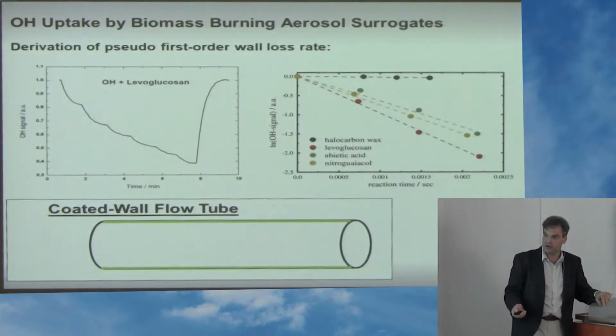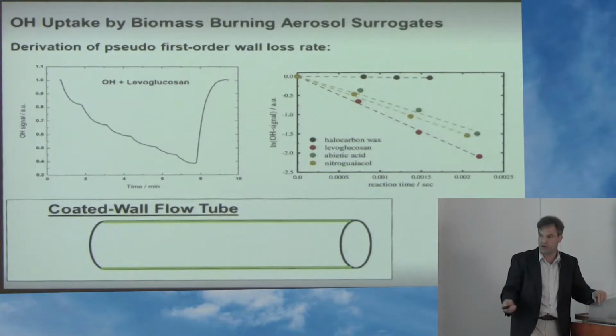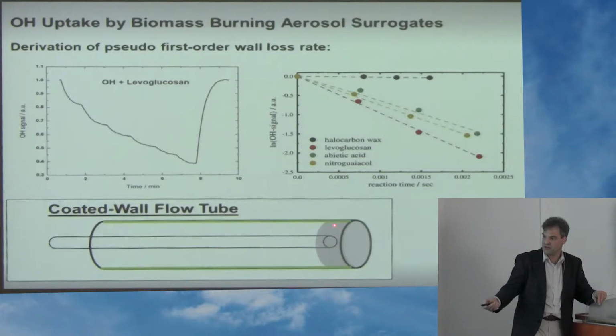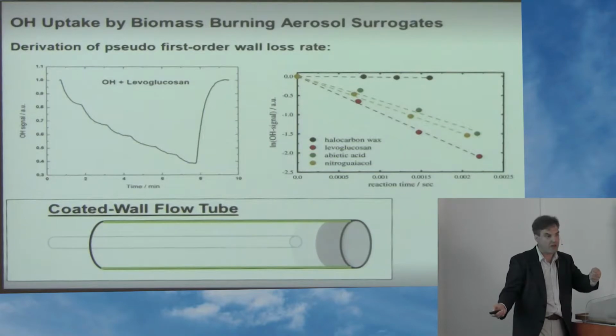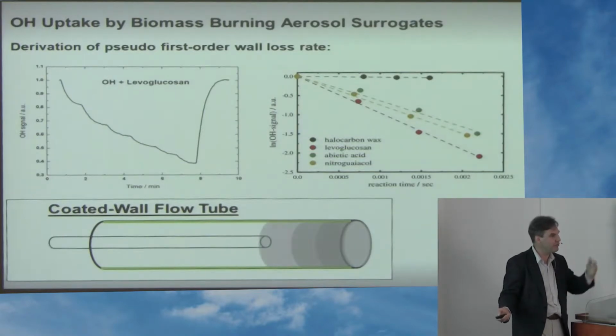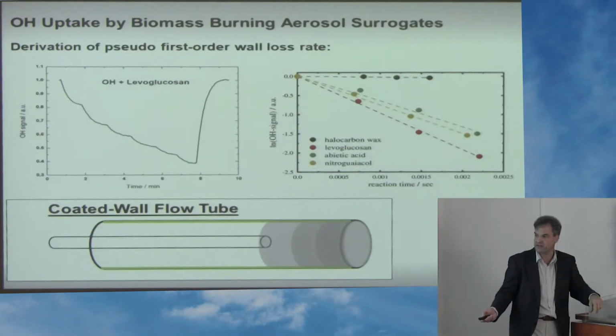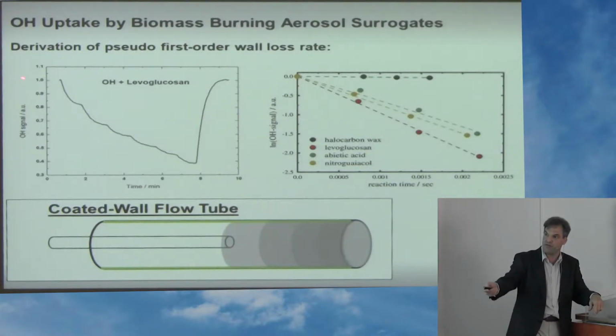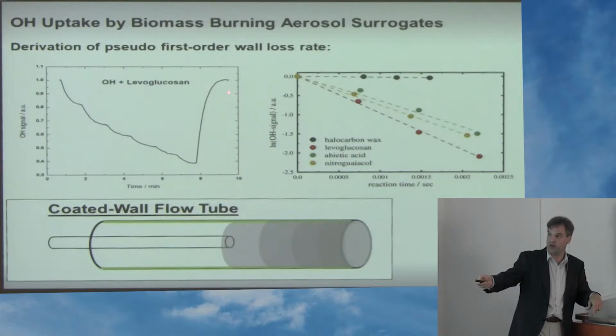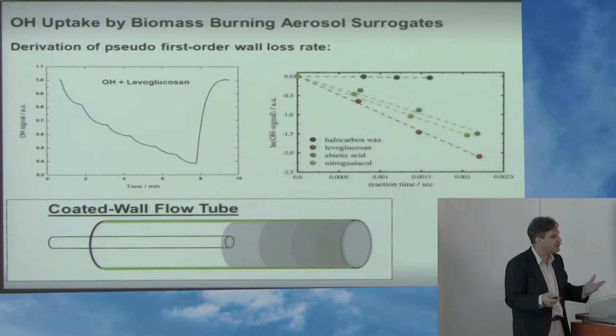Conceptually it's a very simple experiment. We expose the organic surface to OH coming out of the injector, and we pull back the injector. Every time we pull back, we have more reactive surface, so we lose more and more OH as it reacts. If the experiment works, you see a stepwise decrease in OH concentration. If we push the injector back beyond that, the concentration goes up.